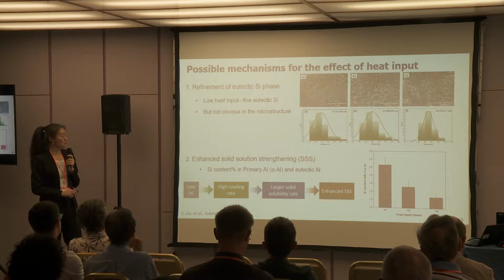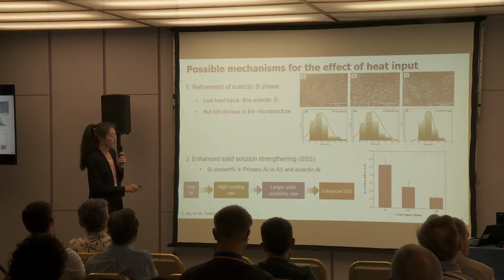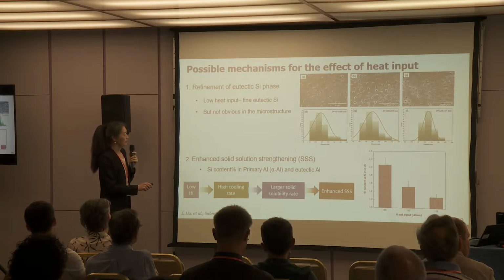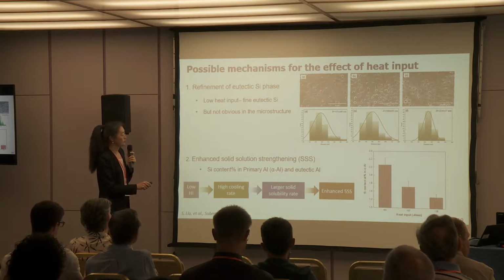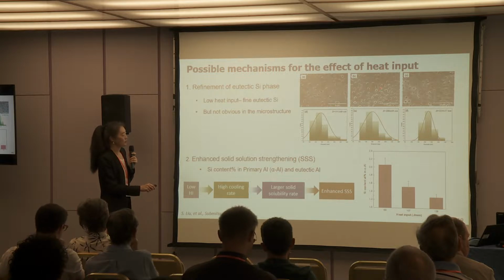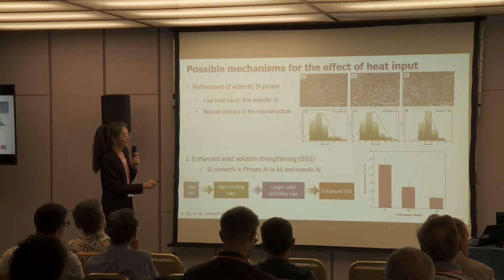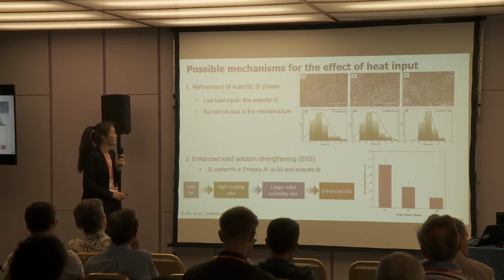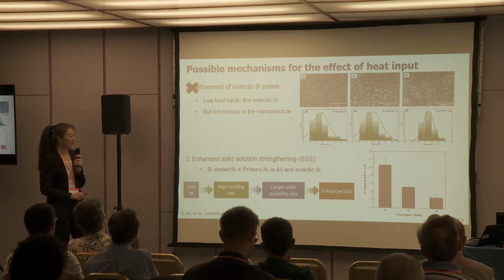And there are two possible mechanisms. First is the refinement of the eutectic silicon phase inside the material. Lowering the heat input may give finer eutectic silicon. However, in our case, we found that all these silicon phases have similar size and the microstructure is pretty similar. So this mechanism will not work.